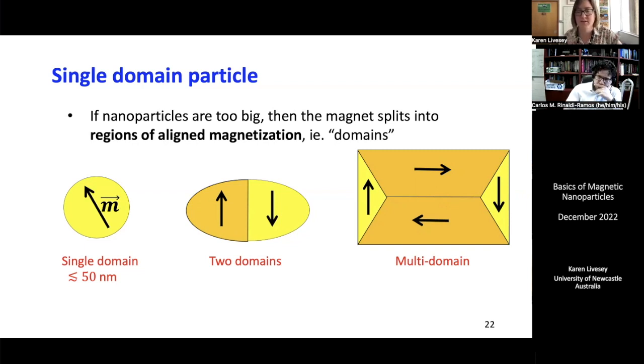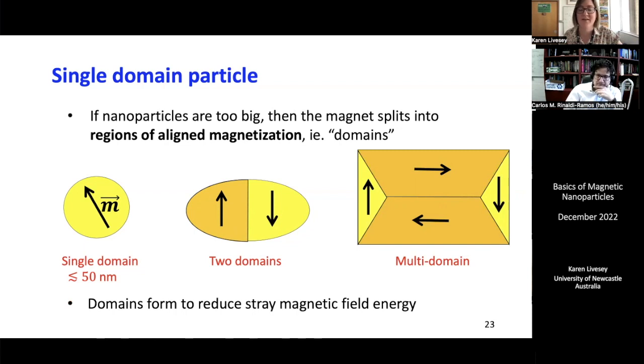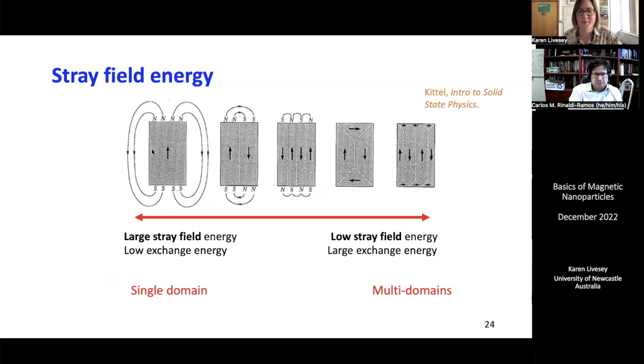So I'm going to show you a picture which is very famous because it's in a textbook by Kittel. So some of you might have seen this picture before. We've got a magnet here, and we've got scenarios where it's split into a different number of domains. So here, for example, there's just one domain, and we see that dipolar field we talked about earlier. That has a lot of stray field energy associated with the creation of that dipolar field. If I split now the magnet into two domains, you can see I have less stray field, and that pictorially is showing us that we have less stray field energy. So we've decreased that energy contribution. And I could keep splitting into smaller and smaller domains.